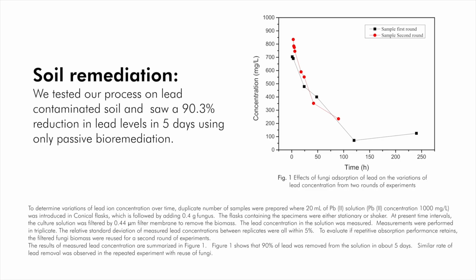So, we kind of brushed over phytoremediation. There were a lot of studies by the EPA in the early 2000s where they funded them, but they kind of stopped funding them because it takes years and years and years for phytoremediation work, and you get percentages usually less than 10%, kind of in the 3 to 5%. So going from 3 to 5% taking years to do, to something that's 90% within 5 days is a huge swing, and that's by changing to different species. This is more of an active approach than the passive approach that we were just looking at, but it's worth more research and more study and finding ways to actually demonstrate this that's useful, not just in the lab, but something that can be demonstrated in real life.